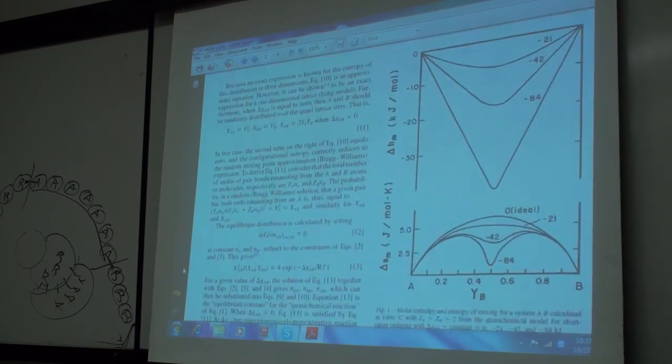By the way, another way of looking at this too is that if we plot the minimum versus X, the mole fraction here, then the minimum can come in different places. Because if it's A2B, it's going to be over here. But replacing X by Y, you always have the maximum ordering when Y is 0.5. That's why we do it that way. So if you plot AB and you use the equivalent fraction, then you always get your minimum at 50%. That's basically what you're doing. You're making a shift in your definition of your composition variable in order to put the minimum always at 50%.